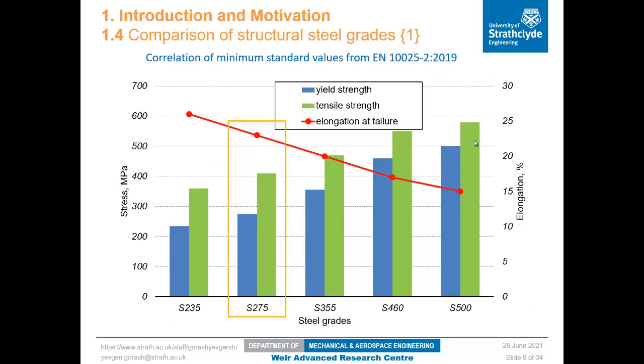When looking at the whole group of structural steel grades, including 235, 355, 460 and 500, this particular grade 275 sits closer to the ductile types of steel with low yield and tensile strength. It means that we should expect higher crack tolerance.